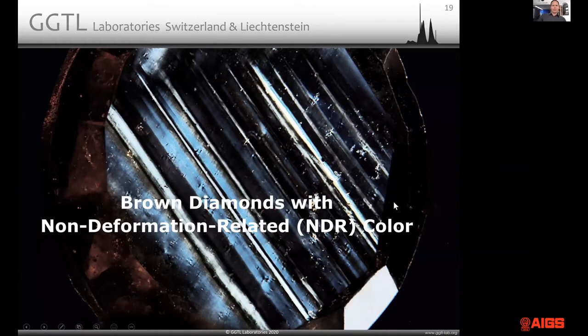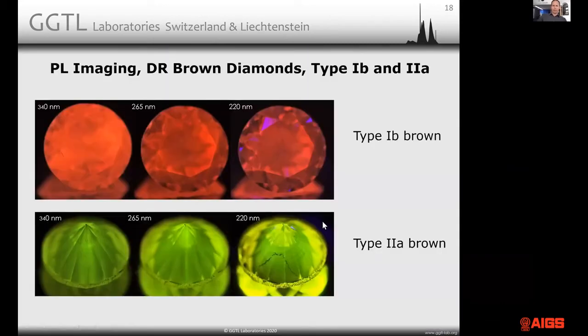There we go. And now here we have PL imaging of type 1B top and type 2 bottom diamonds. Now the bottom one is just a spectacular example because very often type 2 brown diamonds don't have a very characteristic kind of fluorescence image. They actually are very similar to type 1 stones, except that the fluorescence is often much weaker. This stone has very strong H3 centers, even though it classifies as type 2A under infrared spectroscopy. So it has a relatively high concentration of H3 centers. And you can see the dislocations of the diamond in the image at 220 nanometers.